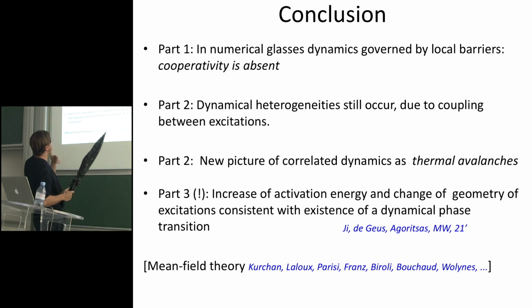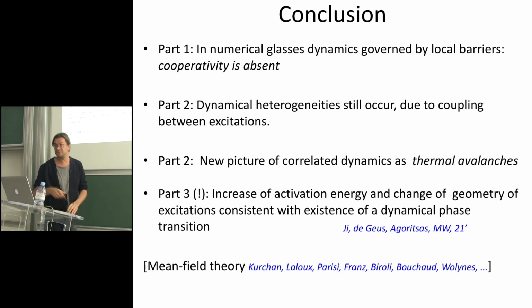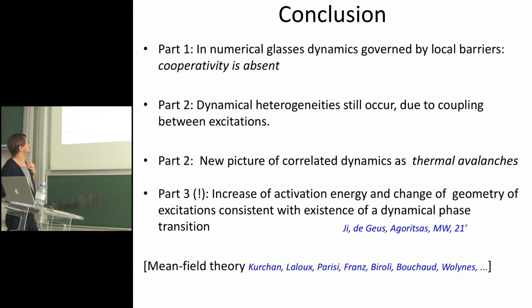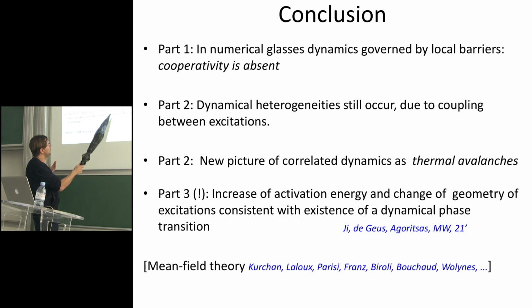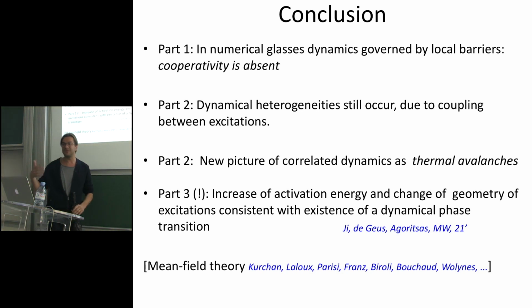So the first result is that at least for those numerical glasses, okay, so now there is a question of universality and so on, but at least for them, there is this quite direct evidence that the dynamics is governed by local barriers, and we don't see any trace of cooperativity. Part two, this is not in contradiction with dynamical heterogeneities, because if you couple those local excitations, you get those heterogeneities. And that suggests a new picture for correlated dynamics, really as thinking about thermal avalanches. And there have been thoughts about thermal avalanches in other problems in physics, actually.